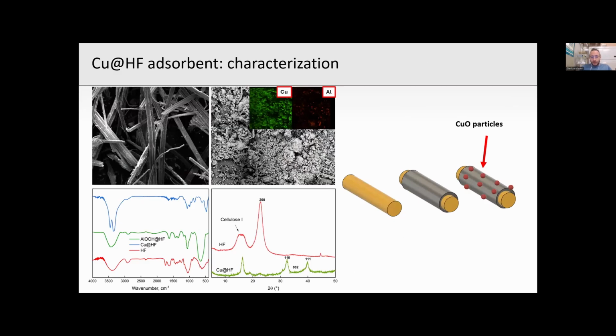Here you can see some preliminary characterization of this novel adsorbent. On the left side, you can see the pristine fibers, and on the right side, the copper oxide modified one. It is possible to observe the typical macro and nanostructure of copper oxide on the surface of hemp fibers. The EDS analysis confirmed the homogeneous presence of copper and aluminum on the surface of natural fibers, while from the spectroscopic analysis such as FTIR and XRD, we can prove the effective presence of this metal oxide.